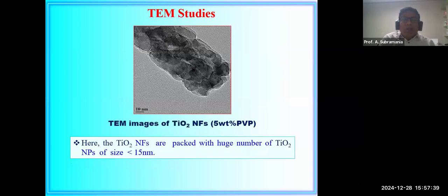This is the TEM image of TiO2 nanofibers. Here the TiO2 nanofibers are packed with a huge number of TiO2 nanoparticles of size less than 15 nanometers. That's why by using this technique, you can prepare interlinked, highly porous materials.